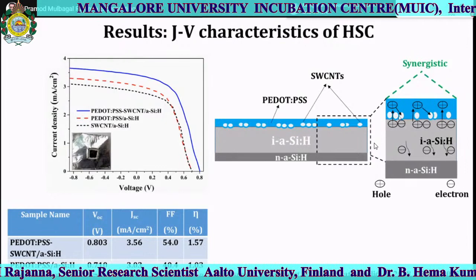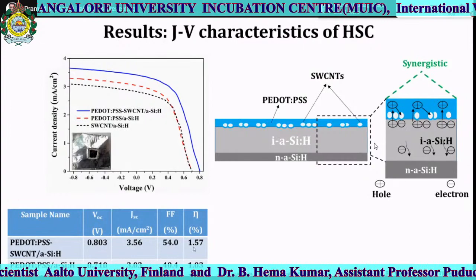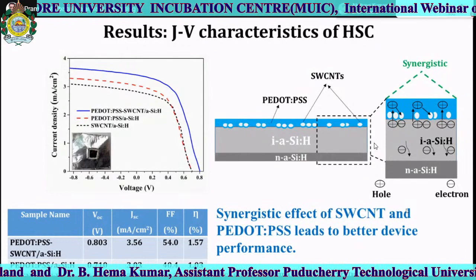Thereby, we have much higher current density and much higher fill factor, and improved efficiency. And due to the uniform contact, we see that the open circuit voltage is much higher than either of them. So it clearly says that the synergistic effect of the carbon nanotube and PEDOT:PSS leads to better device performance.